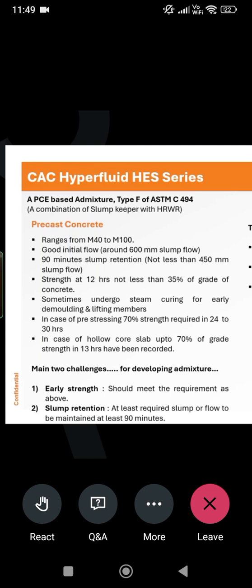So how do we overcome this? By introducing a polymer called early strength polymer. ESP grade polymers have to be used to maintain the required initial consistency, and by combining slump keeper polymers for retention. The required strength at early age is achieved by combining a suitable strength accelerator. These are the methods of getting this kind of specification. That is why I am talking about concrete first and coming later to the specialty of the admixture.